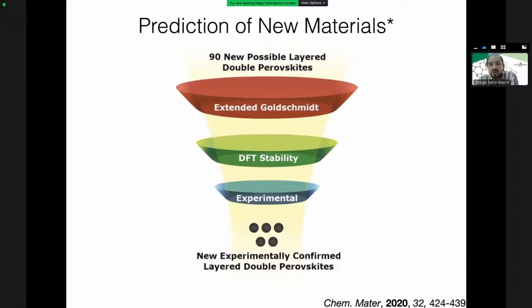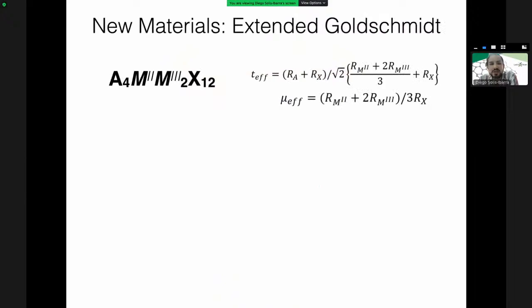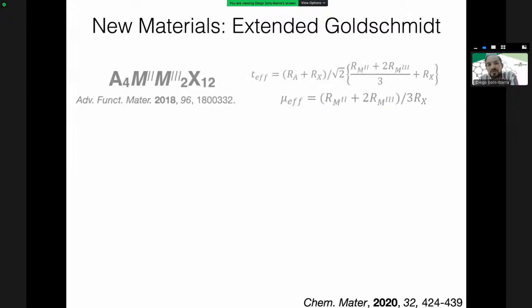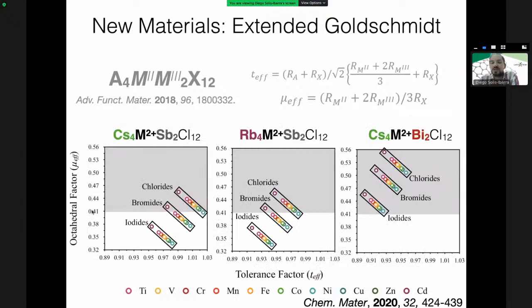So what Raul figured out is that we could do a combination of an experimental and a computational approach to reduce our space and try to see if we can find new materials. First, we did what we call an extended Goldschmidt study, in which, by considering the radii of the different elements, we can discern which ones are more likely to be stable. So pretty much we could see that the ones in the shaded or the gray area are the ones that should be stable according to these criteria. So now we're starting to reduce our search.